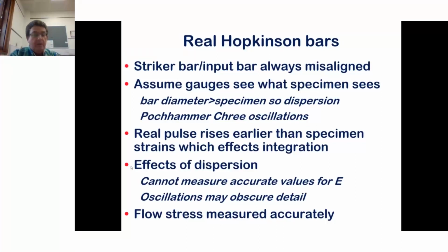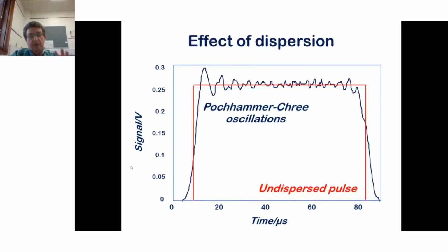So we cannot measure, say, Young's modulus using Hopkinson's bar, but what we can measure with great accuracy is the flow stress. So it's a particular tool for doing strain rates of 10 to the 3, 10 to the 4, and the flow stress is measured accurately. Seen that one before, Pochhammer-Chree, undispersed pulse. So a simple analysis is like the red line. A complex analysis can reflect the more detail in the data. But if what you want is the flow stress of the material, when is that signal nice and flat, you can just draw that line straight through those oscillations and get the flow stress with great accuracy.